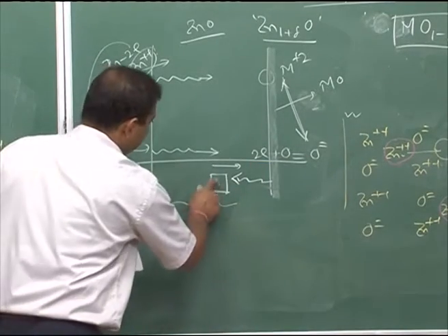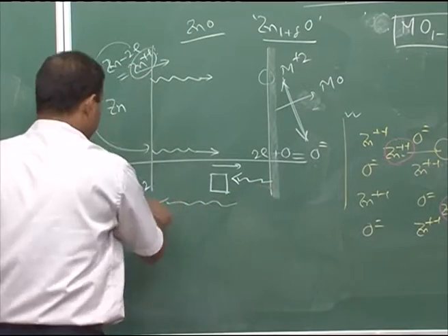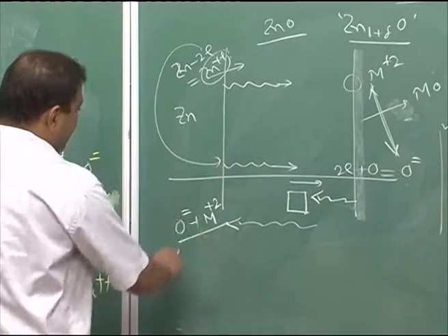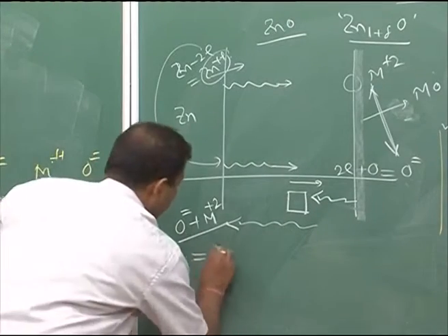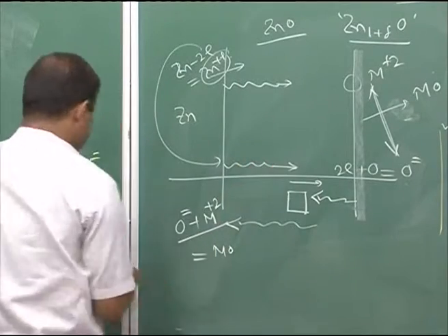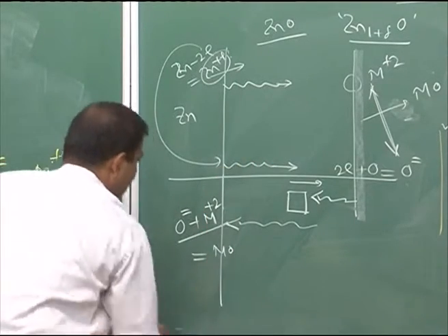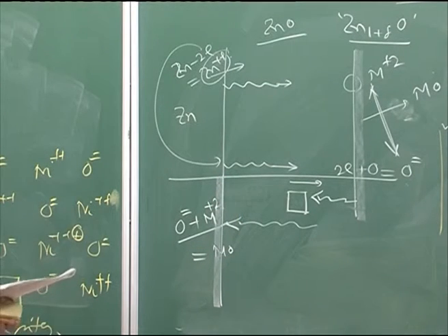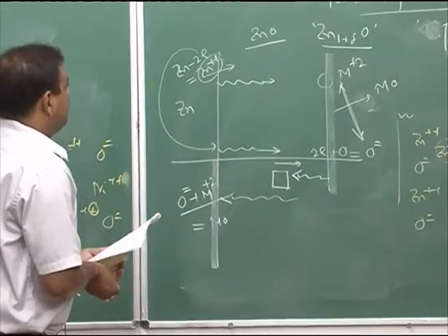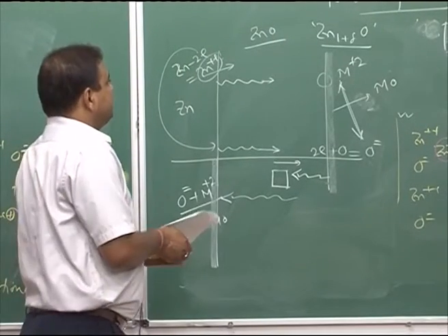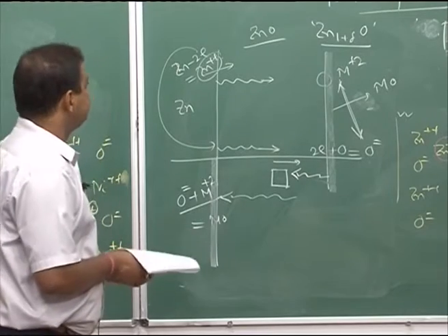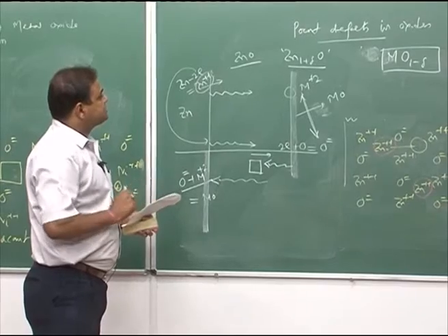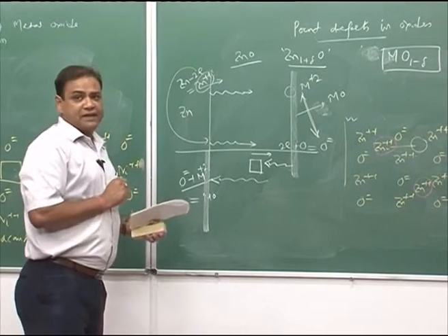So, the anion vacancy will move to this side and the anion will move to this surface. Here the reaction would happen, that means cation and anion will react and form MO. So, in the second case, the oxide growth will take place on this surface. So, this is the explanation of oxidation in case of N type oxides, where either you can have excess metal in the interstitial position or oxygen vacancy.